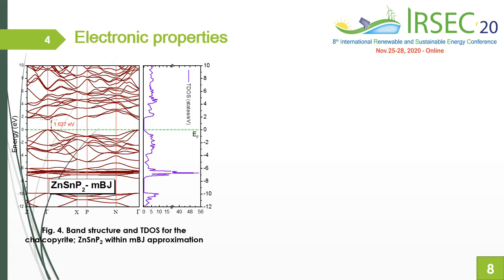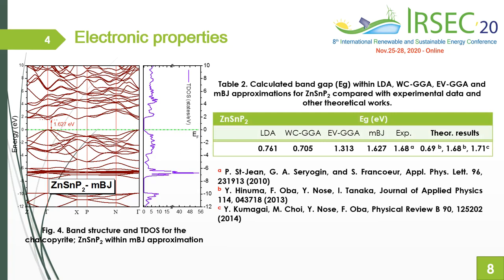In this slide, we calculate the band structures of our material along various high symmetry directions in the first Brillouin zone. It's obvious that this material is a semiconductor with a direct band gap. Table 2 summarizes the calculated band gap within LDA, WC-GGA, EV-GGA, and modified Becke potential approximations for the ZnSnP2, compared with experimental data and other theoretical works.